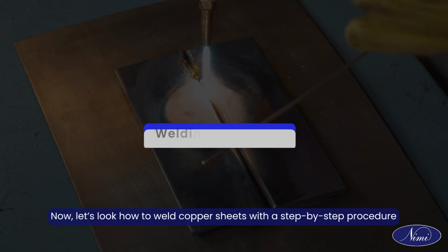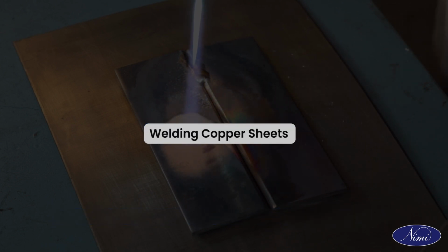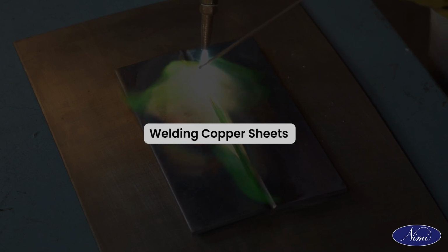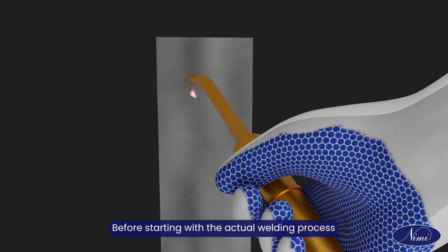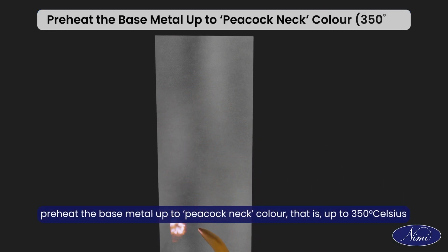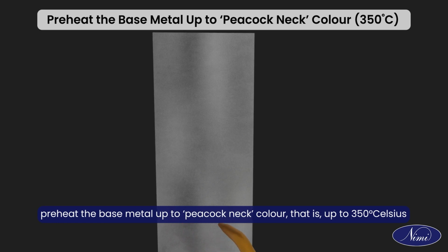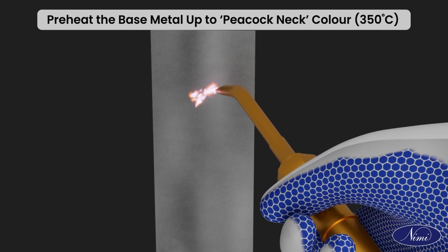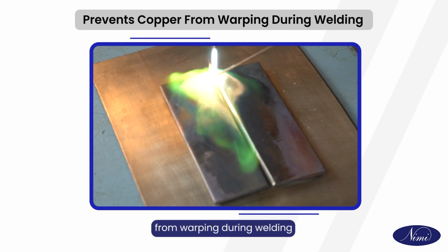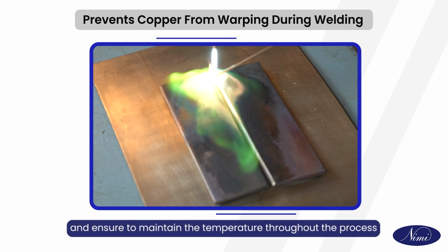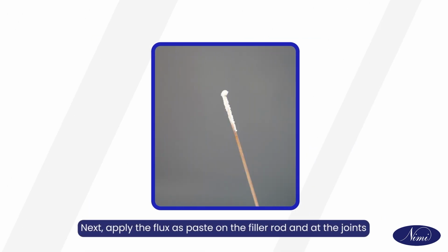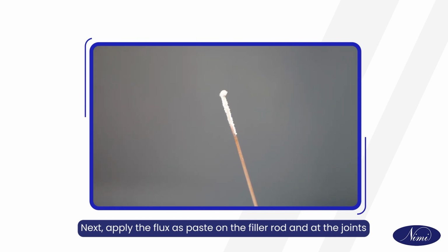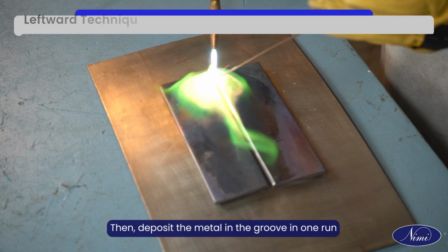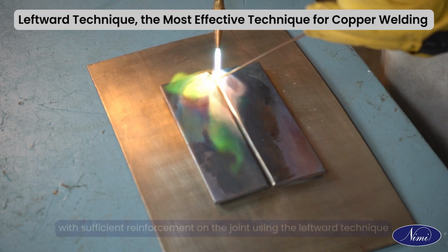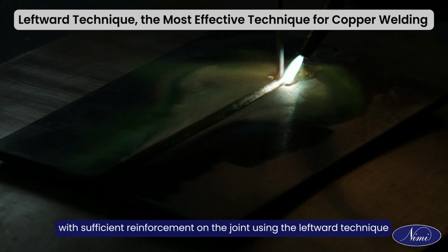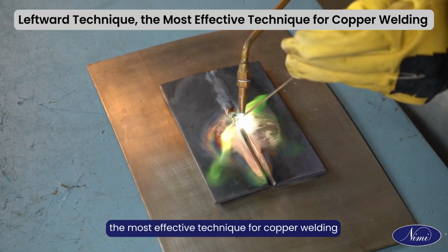Now, let's look at how to weld copper sheets with a step-by-step procedure. Before starting with the actual welding process, preheat the base metal up to peacock neck color, that is, up to 350 degrees Celsius. This process will help to prevent the copper from warping during welding and ensure to maintain the temperature throughout the process. Next, apply the flux as paste on the filler rod and at the joints. Then, deposit the metal in the groove in one run with sufficient reinforcement on the joint using the leftward technique, the most effective technique for copper welding.